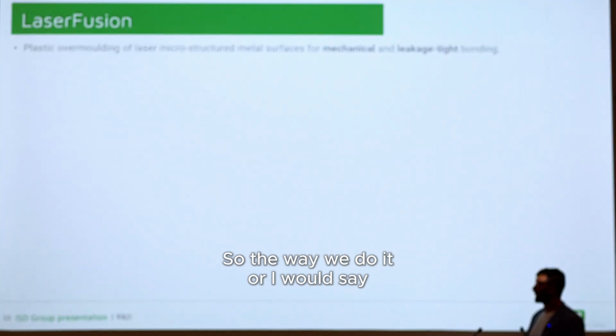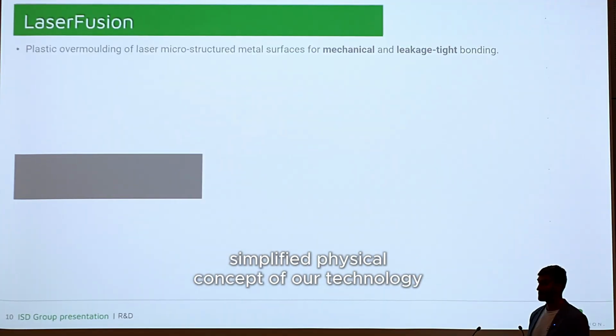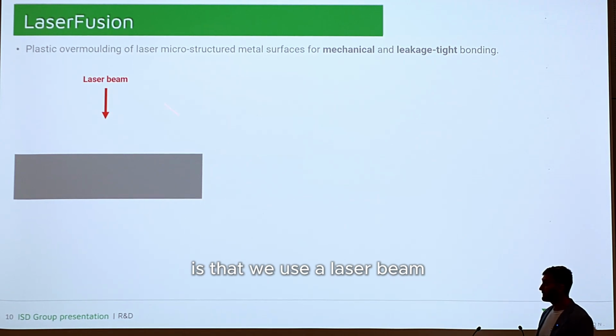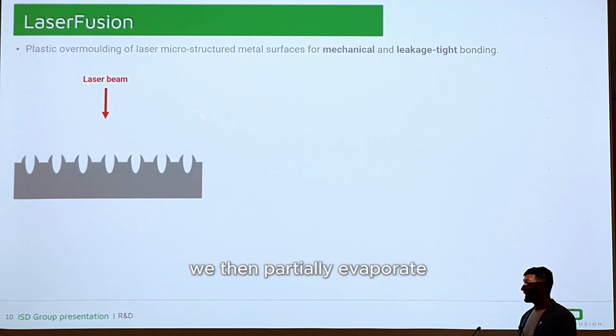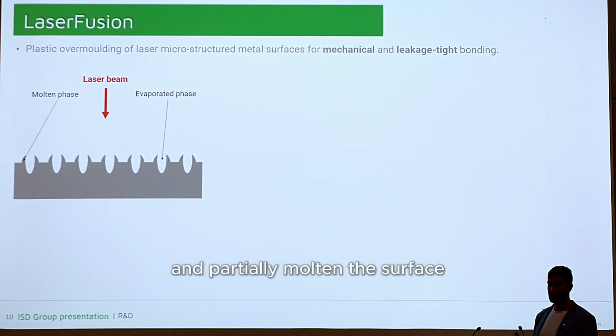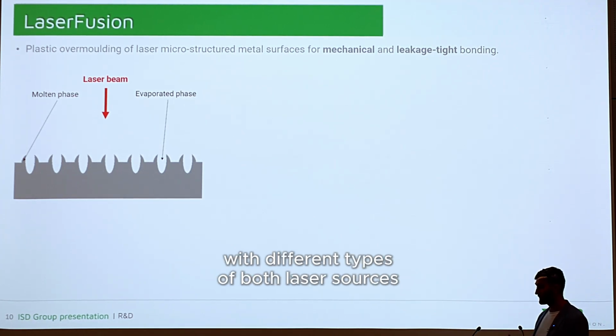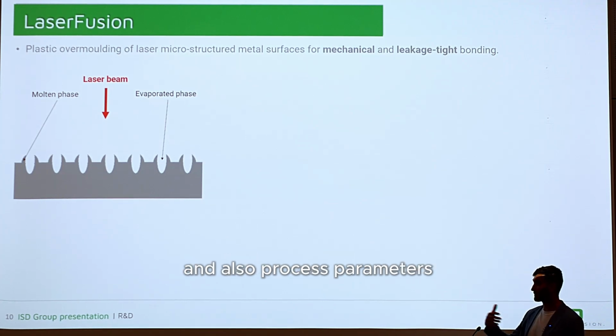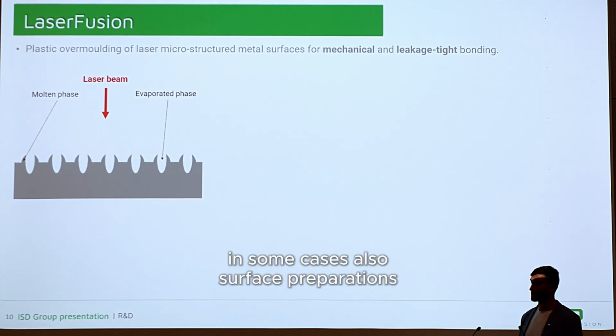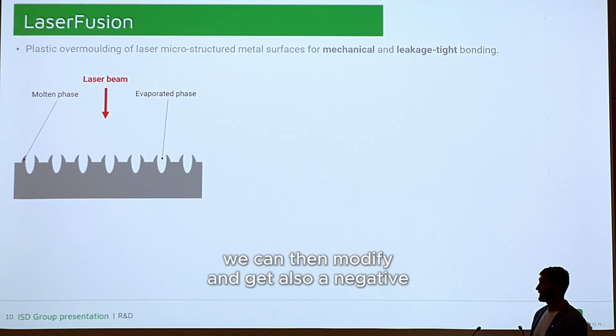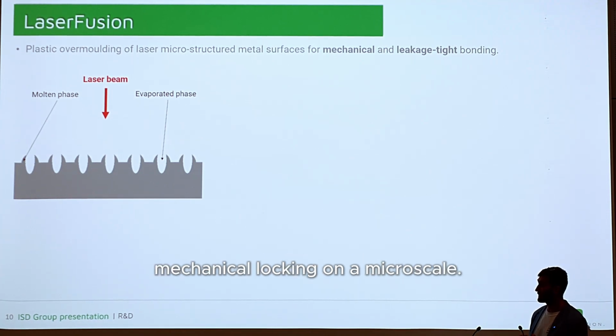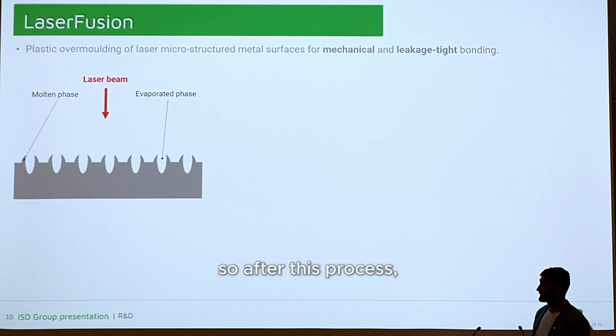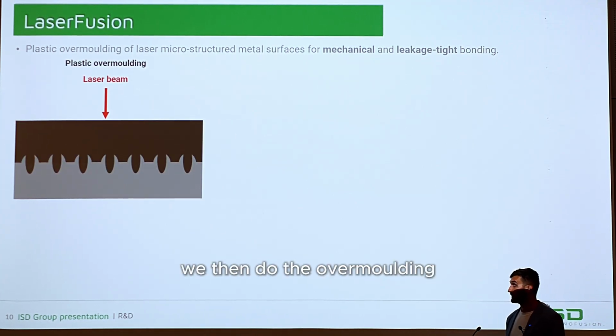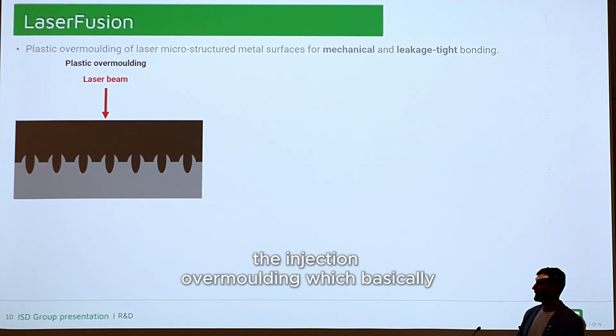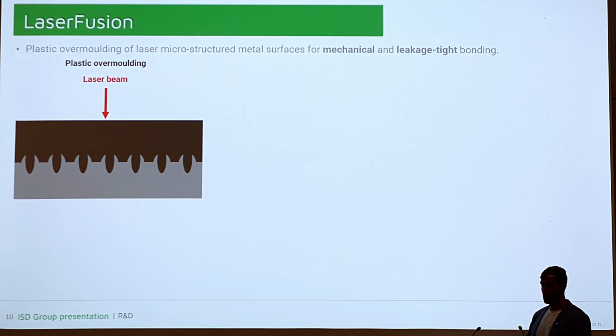The way we do it, in a simplified physical concept of our technology, is that we use a laser beam, which we focus onto the surface. We then partially evaporate and partially melt the surface with different types of laser sources and process parameters, and in some cases also surface preparations. We can then modify the surface and get a negative mechanical locking on a microscale. After this process, we do the injection overmolding, which allows us to reach a micromechanical bond on a micro level between the polymer and the metal surface.